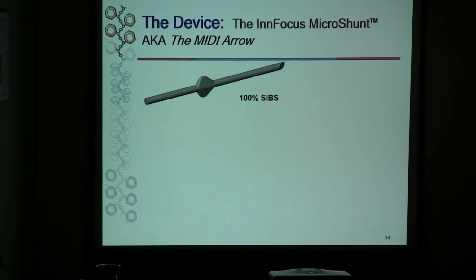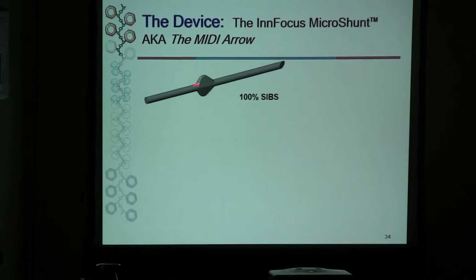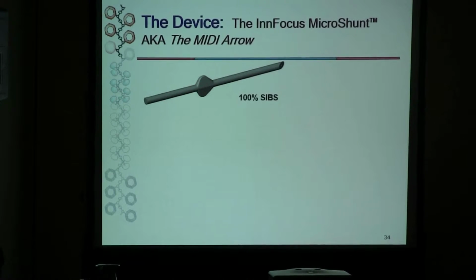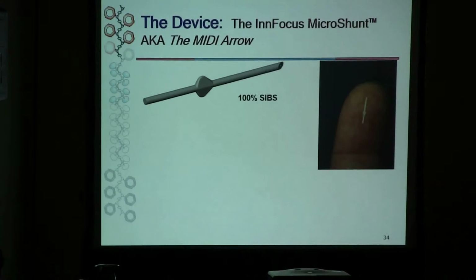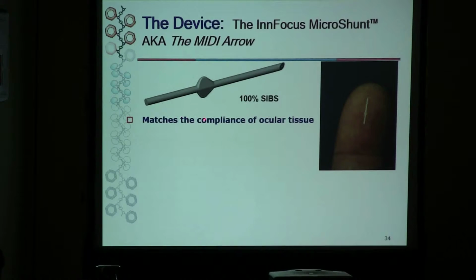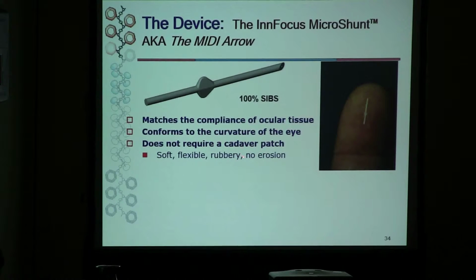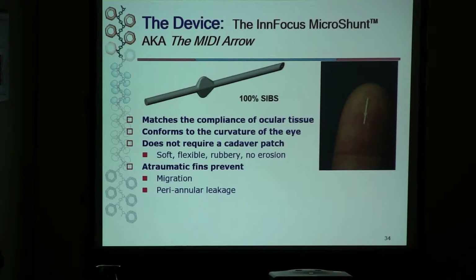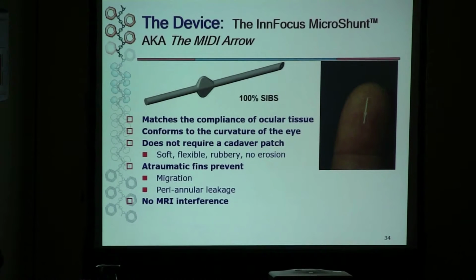So after a few trials and some preliminary clinical studies, we made a tube that had fins on it, 100% out of SIBS, a very floppy material, very small. This is it on my finger. So we matched the compliance of ocular tissue, conforms to the curvature of the eye. It does not require a cadaver patch. It's a soft, flexible, rubbery. There's no erosion. You have atraumatic fins, and these atraumatic fins prevent migration and periannular leakage.